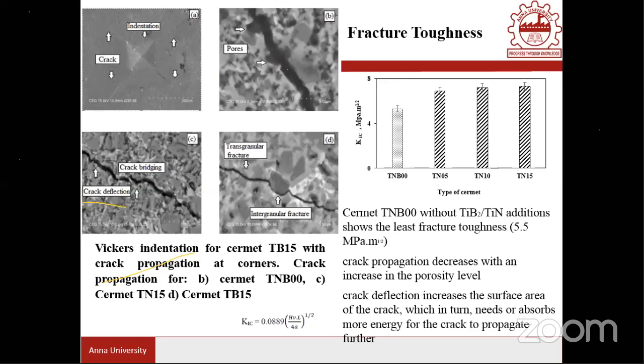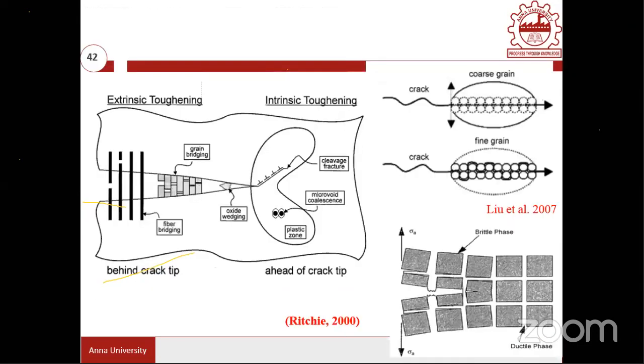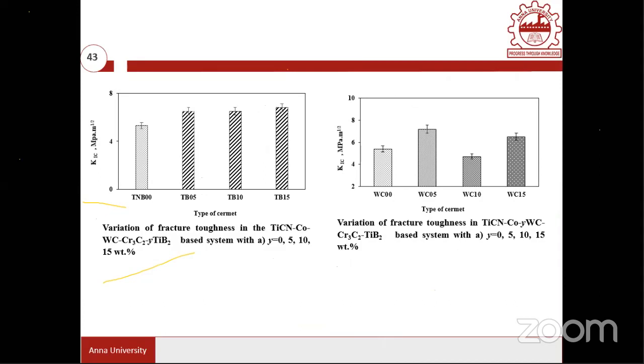Now here, by adding titanium nitride, the fracture toughness value is really increasing. And it is even constant, because there is no improvement beyond 5% addition. And if you look at the fracture toughness value for the varying TiB2 addition, really you have a good value here, more than 7 megapascal root meter.